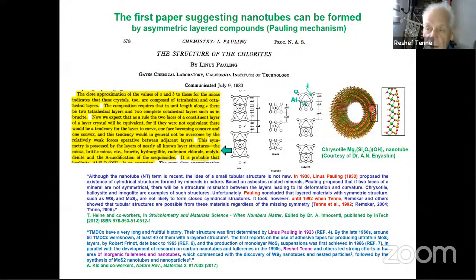So in that respect, nanotubes are not a new animal in chemistry. It's an old animal, and we have to understand that there are different kinds of nanotubes from different layered materials and non-layered materials as well. But if you talk about 2D materials, certainly Linus Pauling is the first proponent of this idea of nanotubes from alumosilicate and magnesium silicate, which are available in nature. He also said in the same paragraph that molybdenum disulfide is a symmetric material like mica. Mica has two silica and one alumina, so it's a symmetric structure on both edges. It won't fold. He said that molybdenum disulfide will not fold and won't form nanotubes. In that respect, he was wrong.